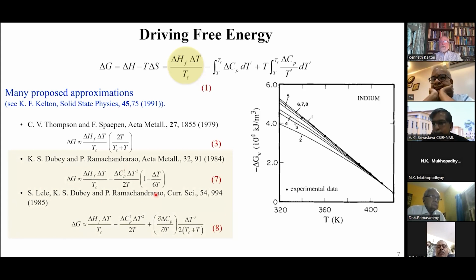If you compare these expressions, here I've compared a lot of other expressions, but these are the actual driving free energy measurements as a function of temperature for indium, the dots. Line 1 is the Turnbull approximation, and it's not too bad, but as you get deeper and deeper in the supercooled liquid, it becomes worse. But 7 and 8 are right here, and they fall right on the data. So these are two actually very, very good approximations. And if you didn't have any data, I would use those.